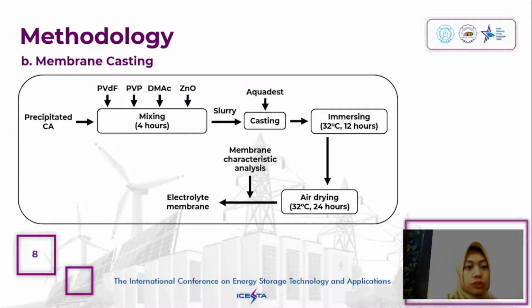The second is manufacturing the membrane. We use casting. We will add the precipitated cellulose acetate into the slurry of PVDF, PVP, DMAC, and ZnO and mix them for 4 hours. And we will cast them onto a glass plate-like surface and immerse them for 12 hours in aquades. And then we will dry them by air drying, and we can analyze the membrane characteristics, and we will get the electrolyte membrane.